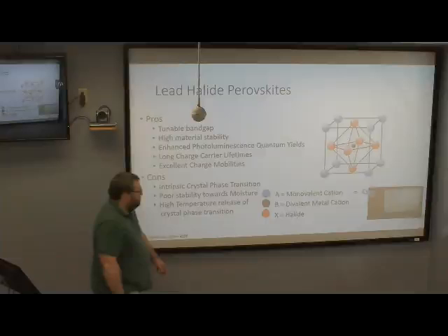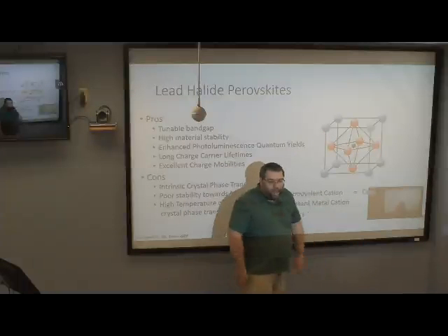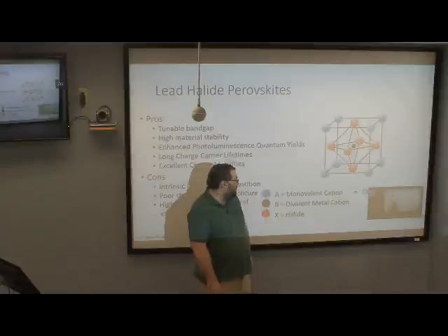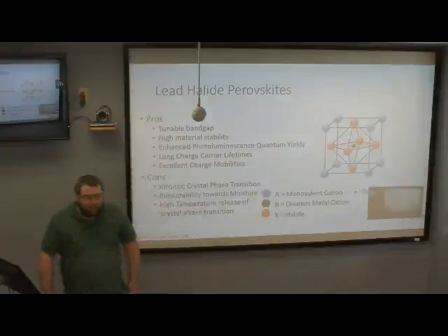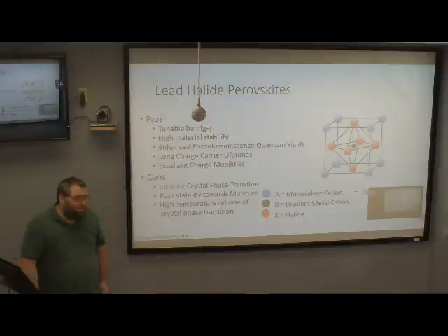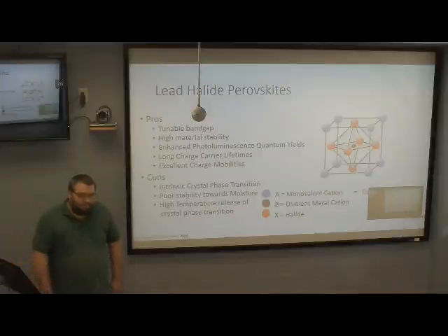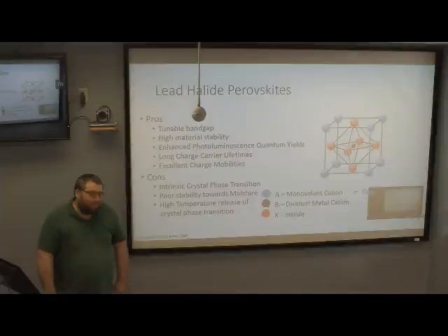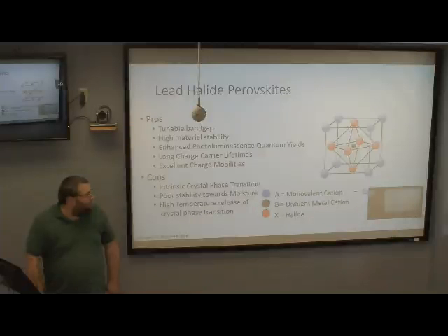The blue and the black atoms here are cations, while the red ones are anions, and it just forms an ionic solid. So it's like a salt. It'll dissolve readily in anything polar. So that'd be a good reference point to mention, just like Dimitri said, referencing things that people already know.